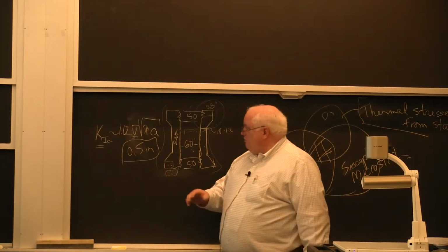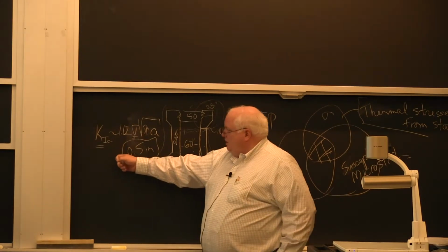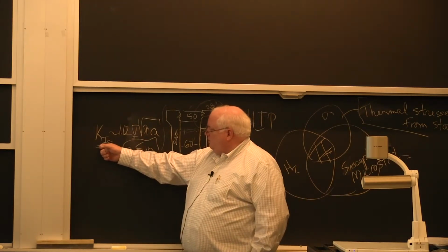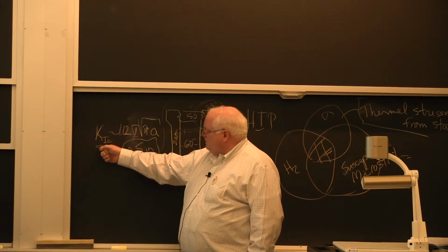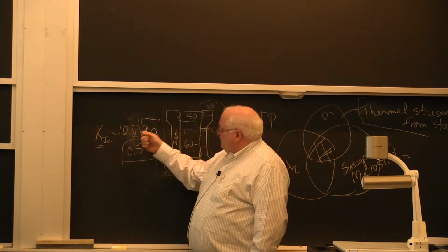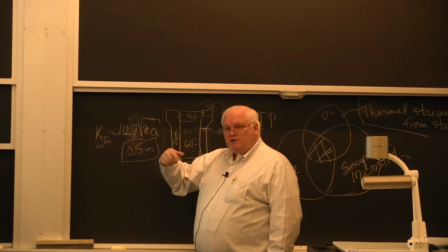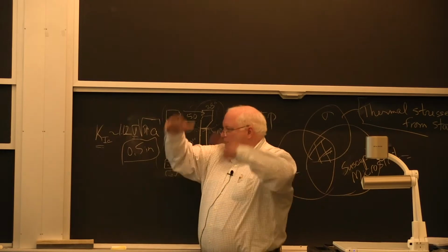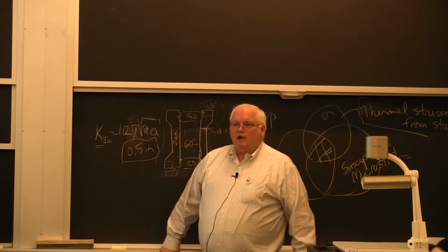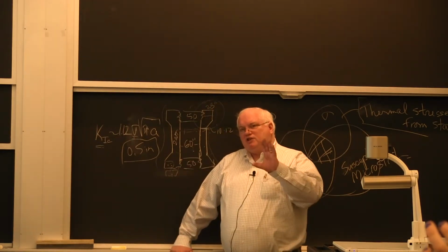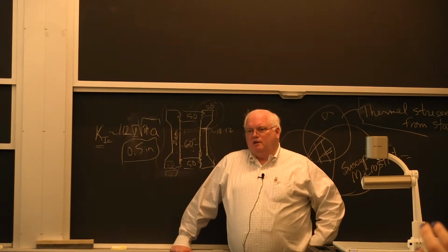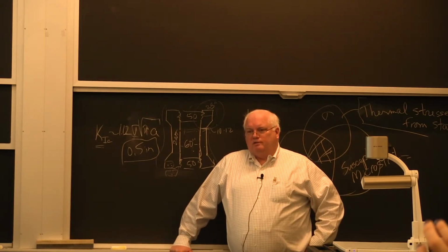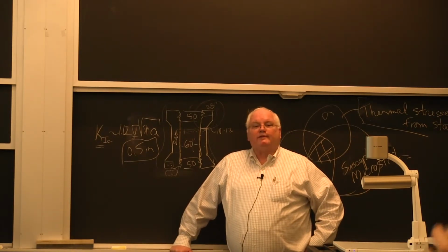But it was all three things, and if you looked at the toughness, your critical flaw size went from 10 inches to 5 inches. If you looked at the stress, it went down to about 2 inches. And if you looked at hydrogen, well, I could explain all kinds of things with hydrogen. I can get up to 75% reduction in strength if I have a lot of hydrogen. Okay? Yes?